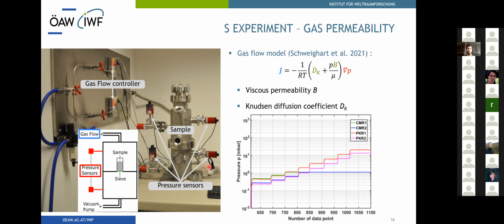The setup comprises a vacuum chamber that is connected to a gas supply of dry air. The chamber itself consists of two separate compartments that are connected by a cylindrical tube. In this tube, the sample is held in place by a sieve. The mathematical model that is used to evaluate the measurements is a combination of the Darcy and Knudsen flow model. It relates the pressure gradient that develops across the sample and is measured by these sensors to the gas flux passing through it. Thereby, the material-specific parameters are the viscous permeability B and the Knudsen diffusion coefficient dk. Mu refers to the viscosity of the gas.